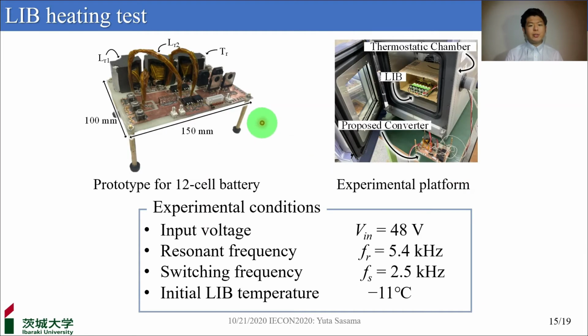Experimental verification. Now, I'd like to show you the results from our experimental verification. We did a lithium-ion battery heating test and a power transfer test using this prototype. We experimented with the aim of battery heating by AC heating in this experimental platform using a thermostatic chamber. Here are the experimental conditions. To satisfy the conditions I described, we designed the resonant frequency to 5.4 kHz, and so we set the switching frequency to 2.5 kHz, which is about half of the resonant frequency. The initial temperature of the lithium-ion battery was minus 11 degrees.